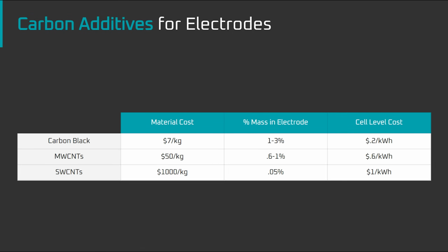OCSiAl provided cost reference figures, which are on screen. They claim that battery-grade carbon black is $7 per kilogram, and 1 to 3% by mass is needed in the electrode. That multi-wall carbon nanotubes are $50 per kilogram, and 0.6 to 1% is needed in the electrodes, and they're indicating a price of $1,000 per kilogram at volume for their single-wall carbon nanotubes, which, depending on the application, only around 0.05% is needed in the electrode.